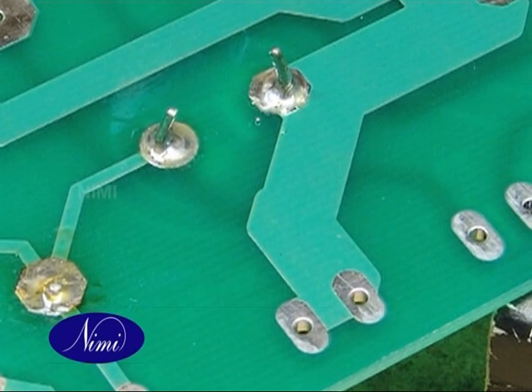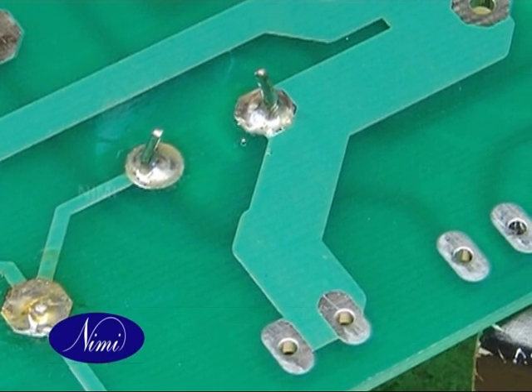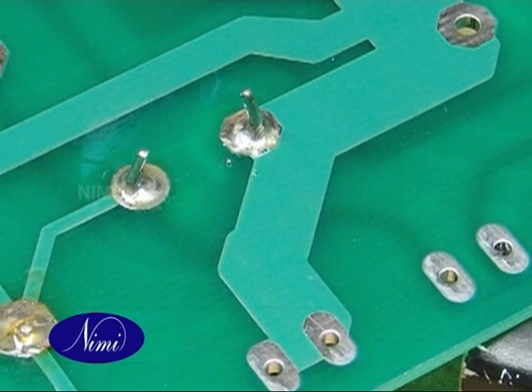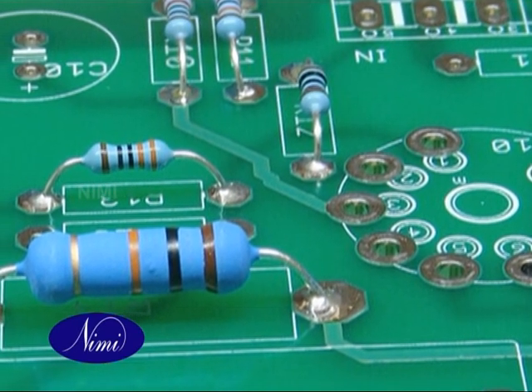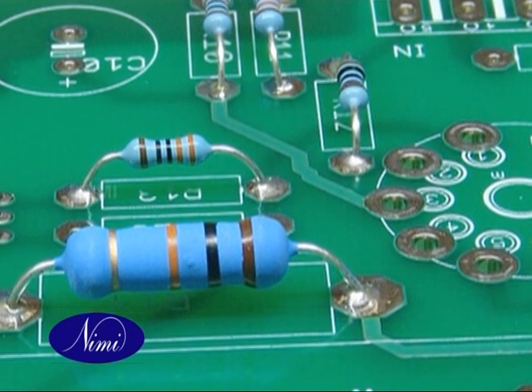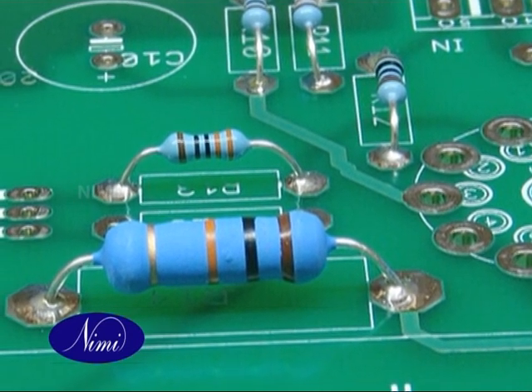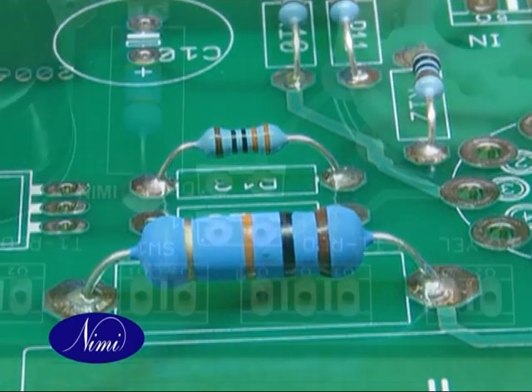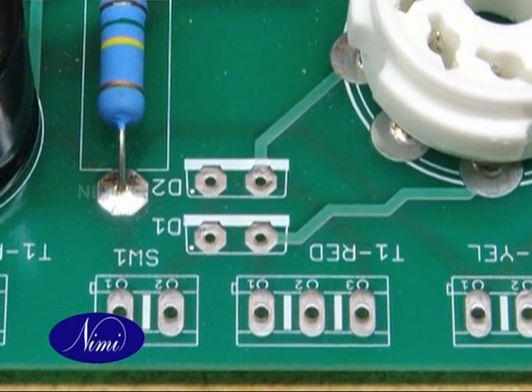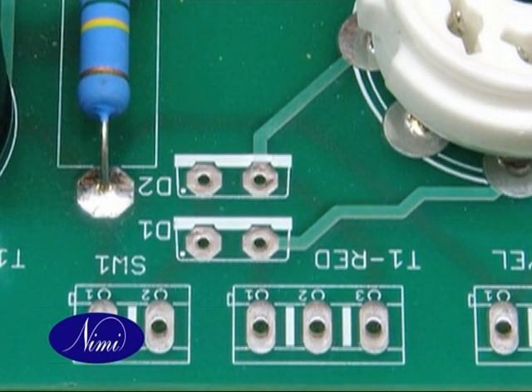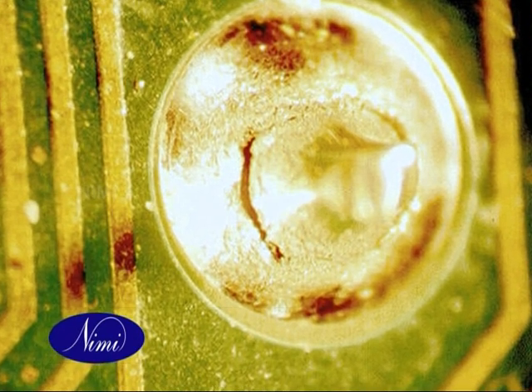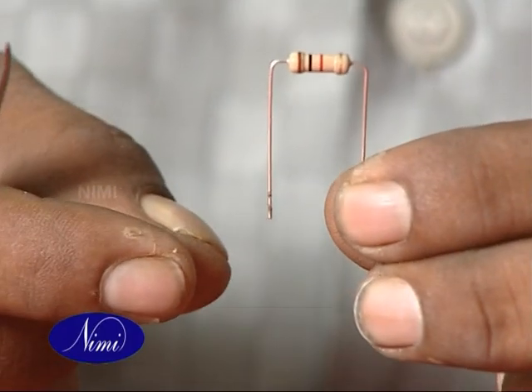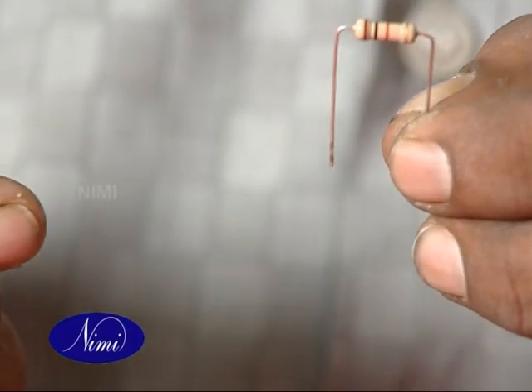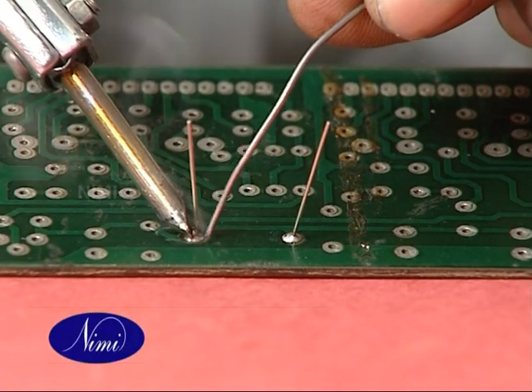The surface of a correctly soldered joint will be glossy, silvery, and uniform in color. The surface texture of a correctly soldered joint will be smooth, even, and non-grainy. There shall be no signs of pitting on the surface of the solder. Temperature defects are caused by excessive or insufficient heating of the joint during the soldering process. It is better to practice bending, trimming, and soldering various types of resistors.